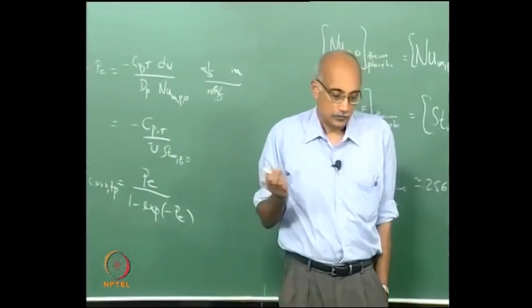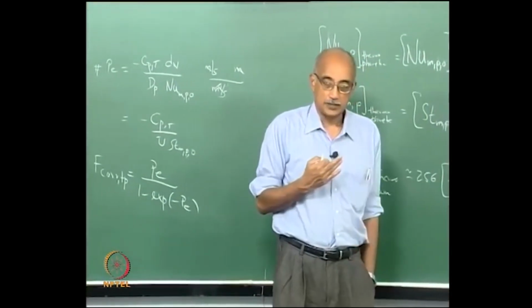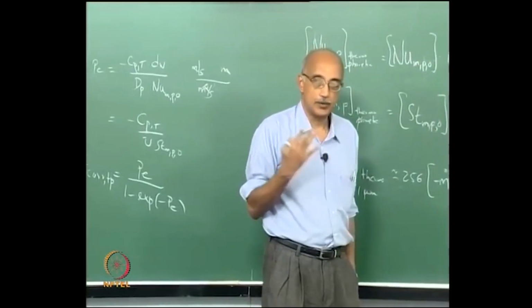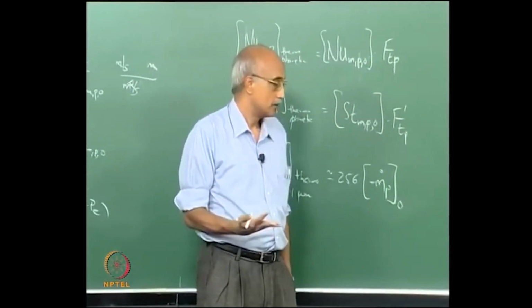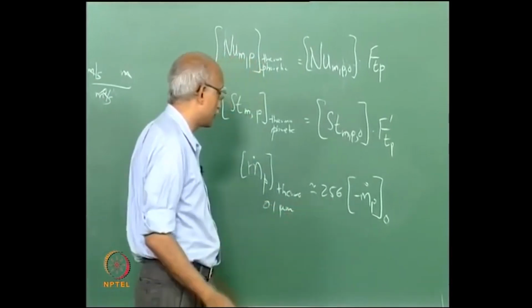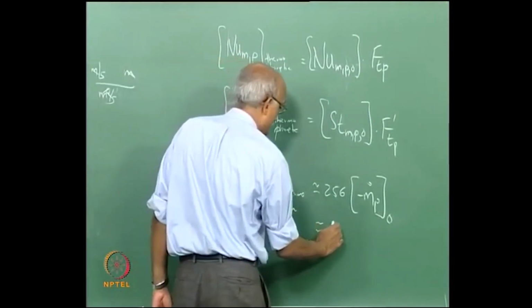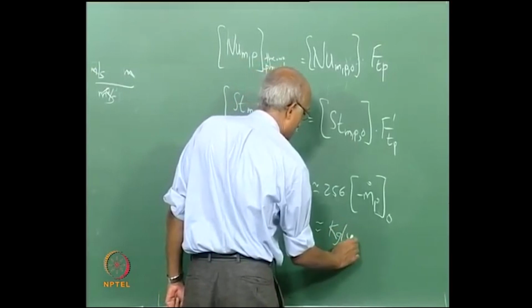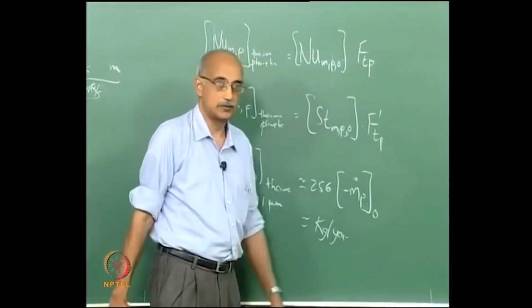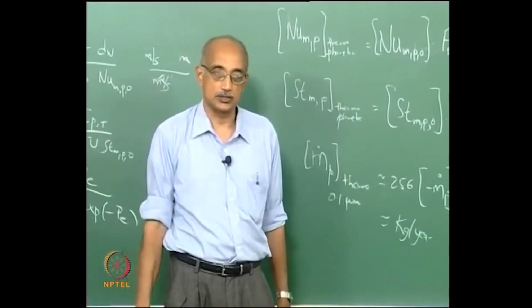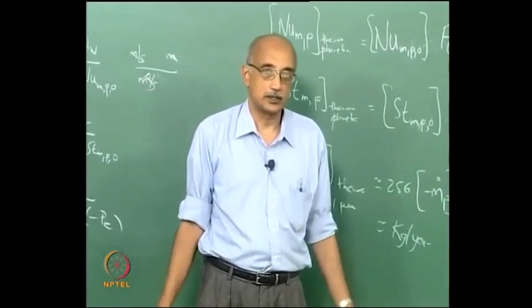Okay, so for particles in the submicron size range, thermophoresis is an important correction factor. So essentially, what we find is instead of grams per year, this leads to kilograms per year of ash material depositing on heat exchanger surfaces, which has been practically observed.